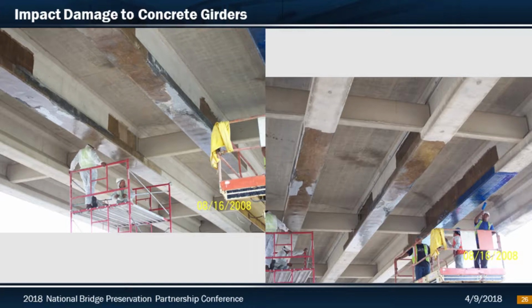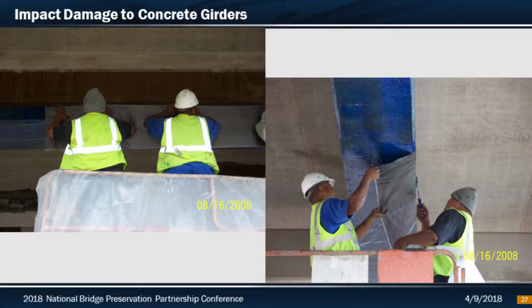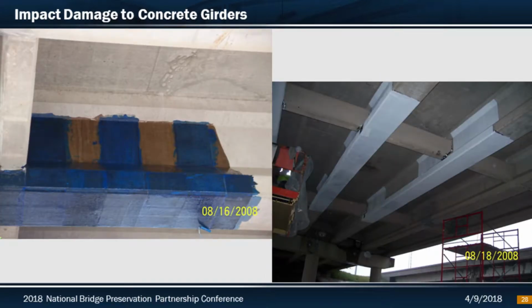Application of your epoxy resin for your undercoat and overcoat is critical for the bond and for the polymer matrix to work well. Again, you can see here the longitudinal bottom flange wrap as well as the U-wraps. U-wraps are usually placed at the termination points, at your splice joints, or on either side of your diaphragms.